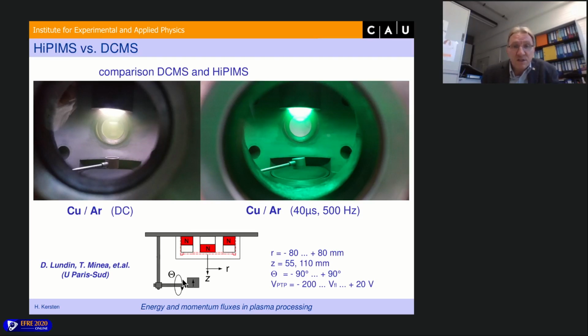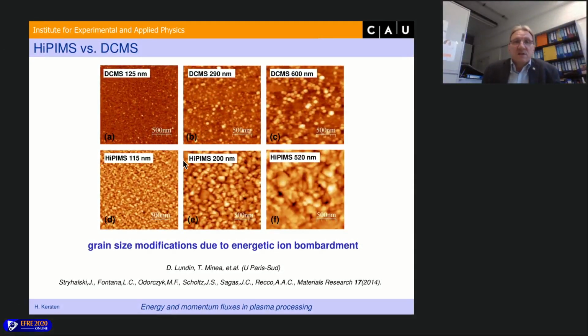As you can see here, we move the thermal probe radially, axially, and angularly in order to map the energy flux or power density for deposition of thin films. And this of course influences the grain structure. For instance, here is the grain structure of a deposited metal film for DC magnetron, and here for HiPIMS magnetron. The grains are much larger in the HiPIMS case than in the DC case.